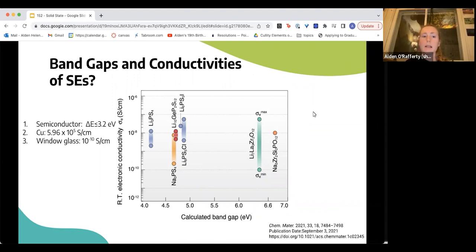The cutoff for what's considered a semiconductor is typically below 3.2 electron volts. These are way above that, meaning even if you add some energy, it's going to be really hard to excite a significant amount of electrons up and hop that band gap. For reference, silicon is like 1.1, 1.2 electron volts. So they have a very large band gap. And how does that affect their conductivity? Well, as we'd expect, they're not very electrically conductive, which is what we wanted.